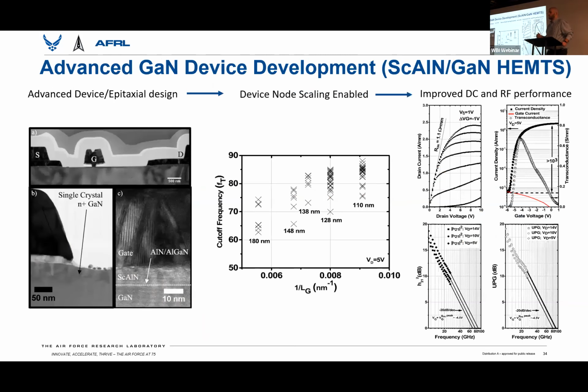And then at a little bit of a lower level, more of an R&D level, we are also looking at advancing field effect transistor design and epitaxy. So here is an example of an advanced GaN epi stack called scandium aluminum nitride. Normally, a GaN HEMT can be aluminum gallium nitride on GaN, scandium aluminum nitride on GaN. What the material stack itself allows is for you to maintain the charge in your device, but with a much thinner material stack.